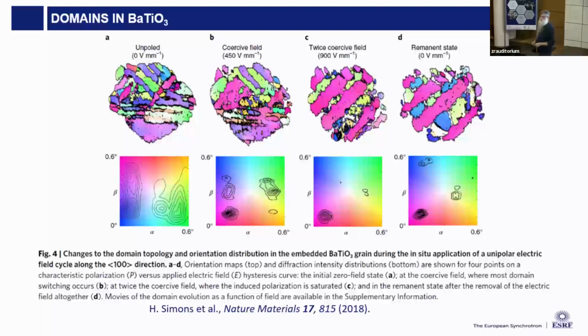And then you start to remove the field, and the basic domain state is conserved, even though the domains shrink. And that is something we can do. We can loop through these domains and follow it in situ. Again, at the bottom, you have the reciprocal space maps, which have been known from macroscopic studies, and you can very nicely relate these two.